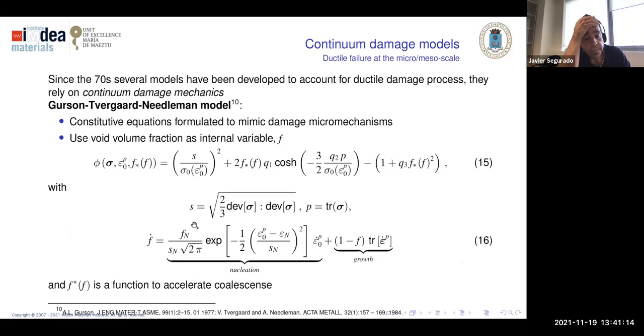Okay, what is behind? Behind we have a continuum damage model, and if you are familiar with continuum damage mechanics, you have for sure heard about the Gurson model or the GTN model. The Gurson model is a plasticity model that, in addition to standard plasticity, takes into account the evolution of porosity. So the material does not only plastify, but due to the plastic strain, if we have some porosity, this porosity grows, so the volume fraction of pores grows.